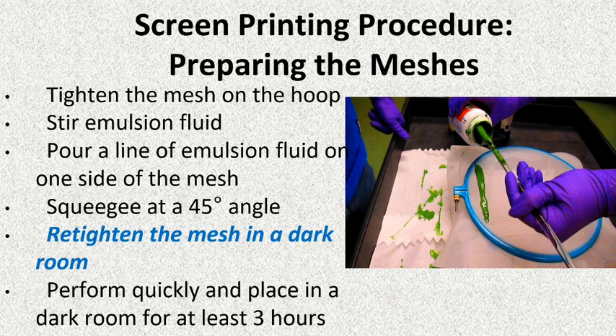So how screen printing works is you have your material that you want to screen print on. You have a mesh-made template that you run paint or other things through, and it actually prints it onto the material, kind of like a stencil. And so, to prepare the meshes for these stencils, the first thing you need to do is tighten the mesh on a hoop, like here, stir the photo emulsion fluid, this stuff right here, and pour a line of photo emulsion fluid on one side of the mesh, then squeegee it at a 45-degree angle across the mesh.